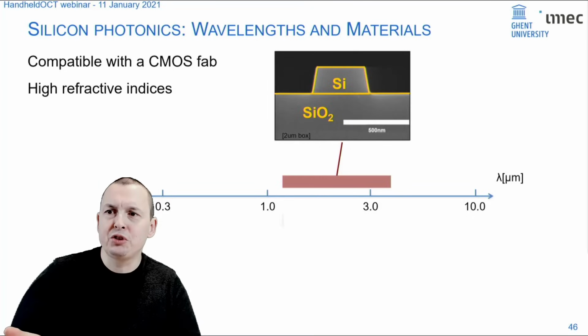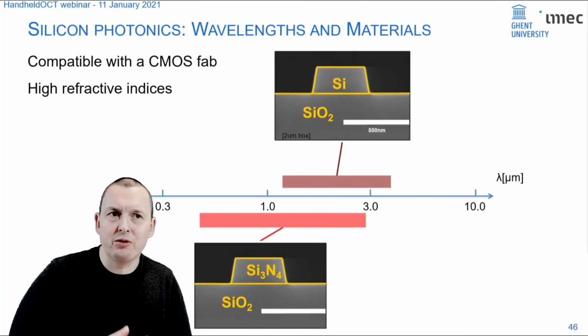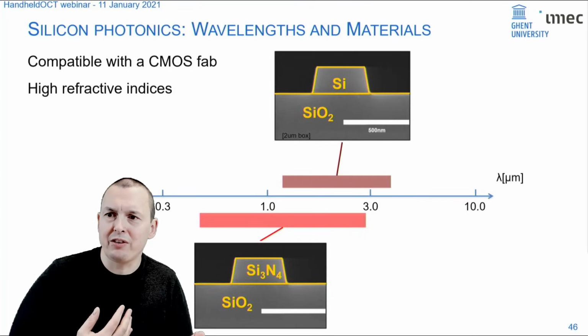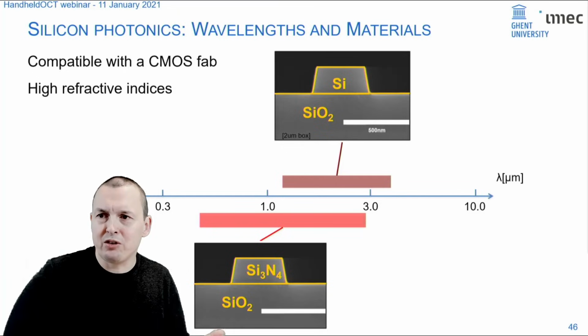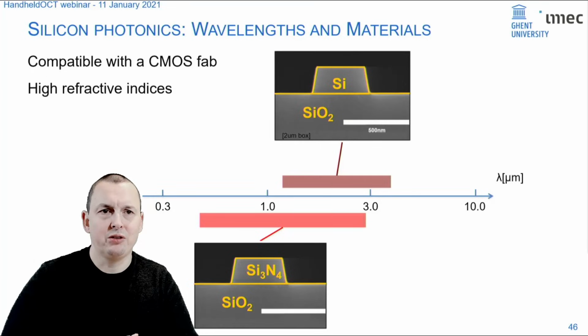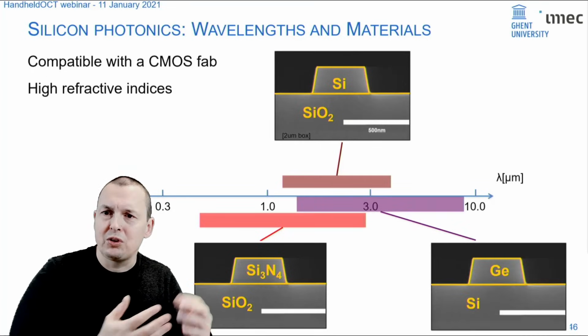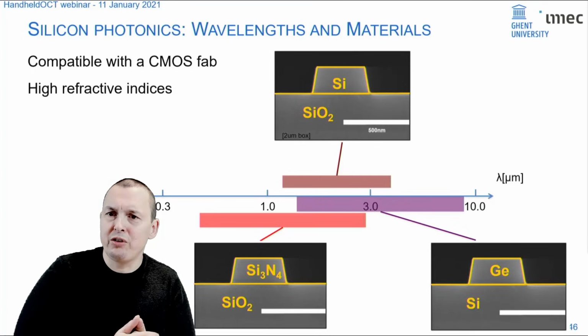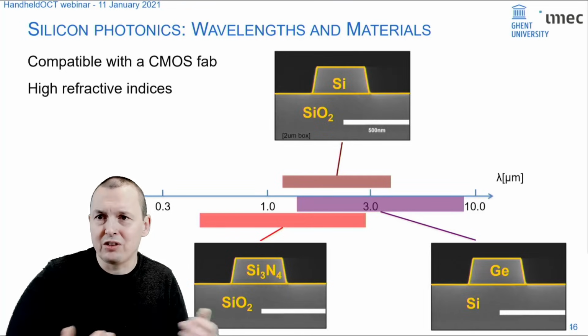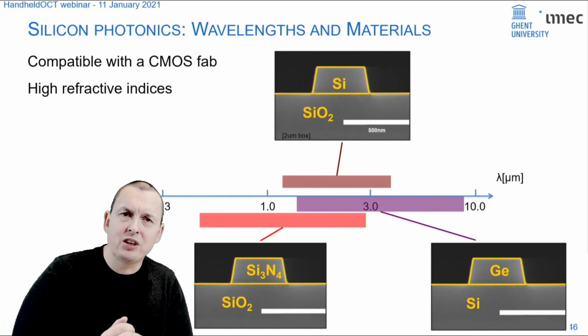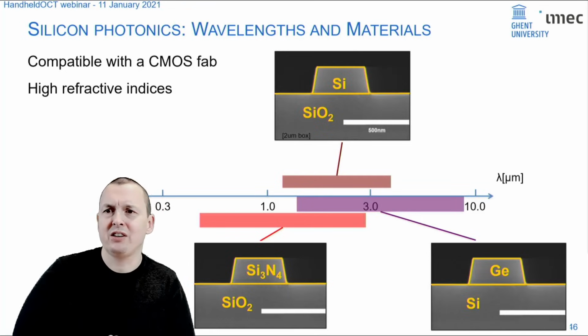But if you want to move to shorter wavelengths, you can, for instance, start using materials like silicon nitride, which is transparent for much shorter wavelengths. The index contrast is not as high as in silicon, but it's quite good. If you want to go to longer wavelengths, you can start using germanium, which is since 15 years an accepted material inside a CMOS fab.